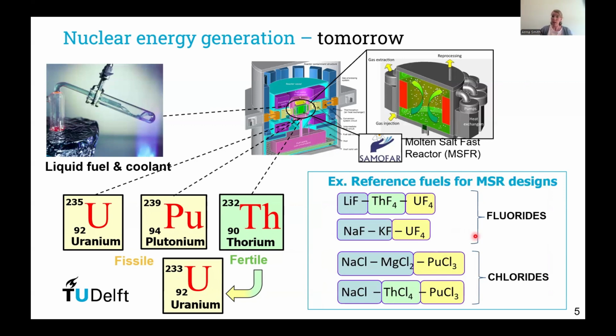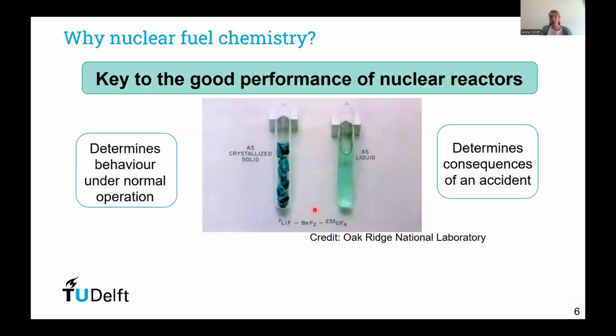At this moment, two types of salts are being envisaged among the MSR community. Some reactor designs are based on fluoride mixtures, and other reactor designs are based on chloride mixtures. Usually, there are 2 or 3, maybe 4 end members in these mixtures with a fissile element, for example, uranium tetrafluoride or plutonium trichloride, an alkali, for example, here lithium fluoride, but it could also be sodium fluoride, potassium fluoride, or if it's a chloride, sodium chloride mixture, and maybe a fertile element if there is thorium in the mixture.